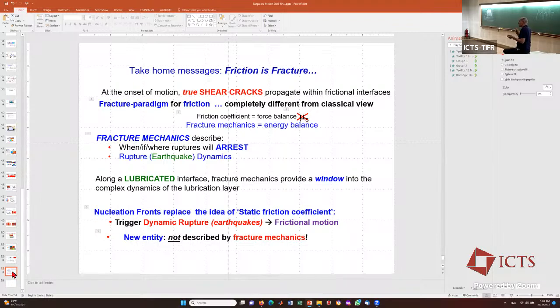I didn't mention this, but the fracture energy is just a small amount of the total dissipation. Most of it is in frictional heating. Remember, I subtracted away the residual stresses, but the residual stresses are large, so I still have to move the back of the material. So I think that's what they're doing, and they're interpreting it as fracture energy. But I think that different people mean different things when they use the same words.